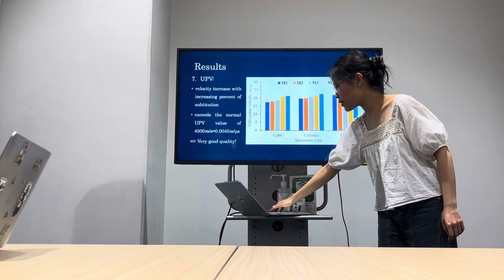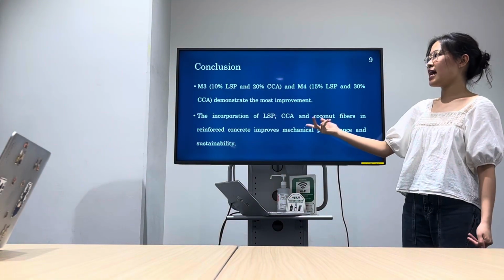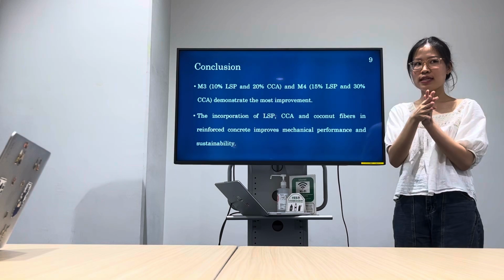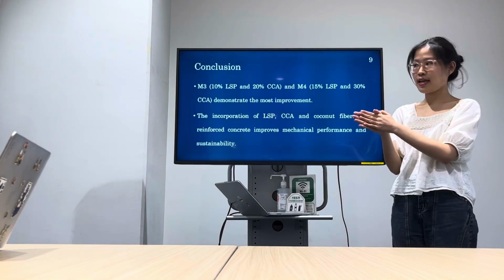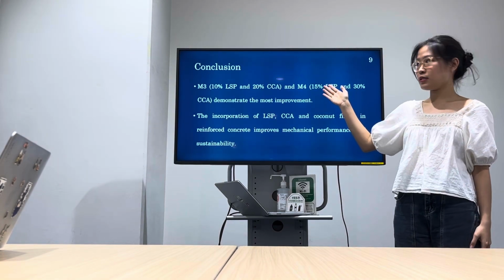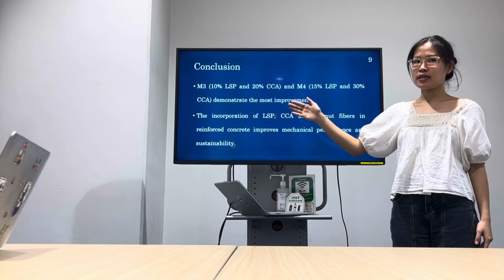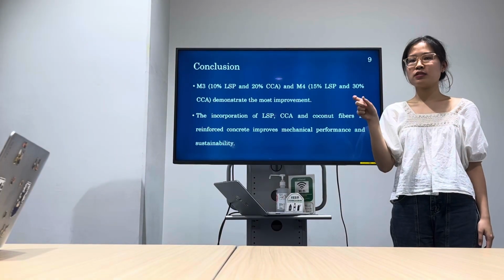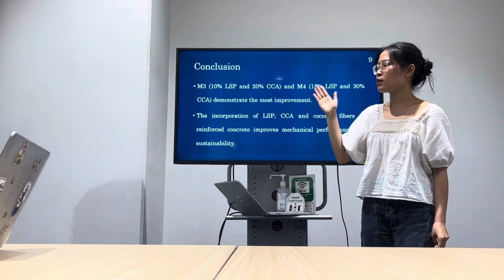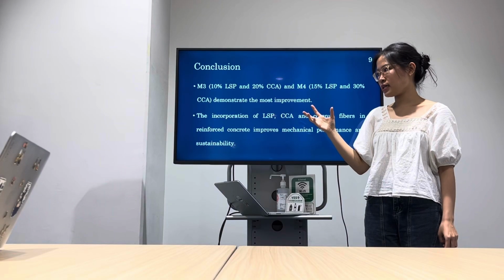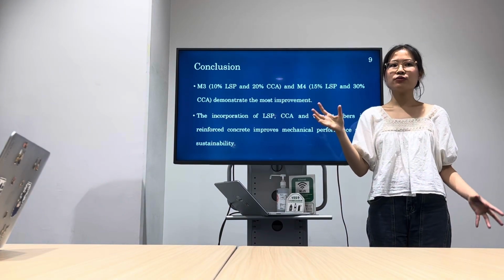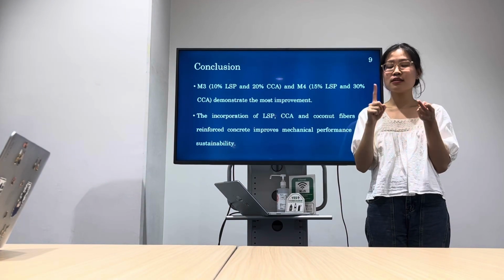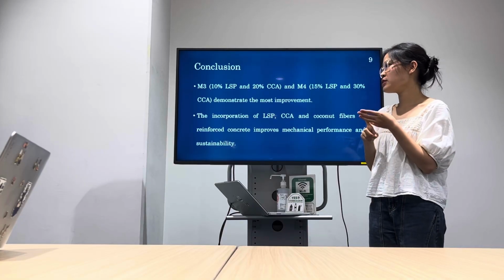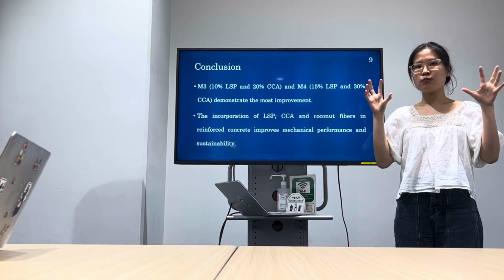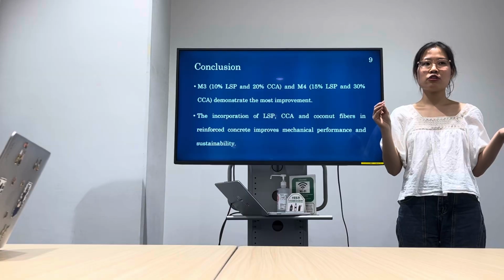And that's why we can conclude that M3, 10% LSP and 20% CCA, and M4, 15% LSP and 30% CCA, both of them at 0.2% coconut fibers, demonstrate the most improvement out of all mix IDs. We can also conclude that the incorporation of LSP, CCA, and coconut fibers in reinforced concrete improves not only the mechanical strength, but also the sustainability of concrete.